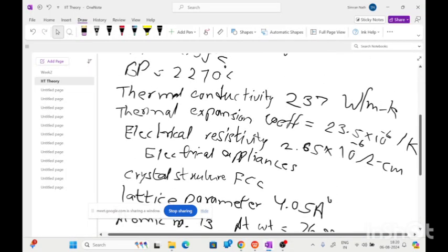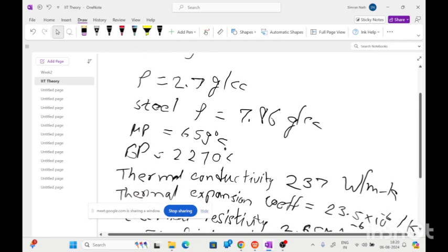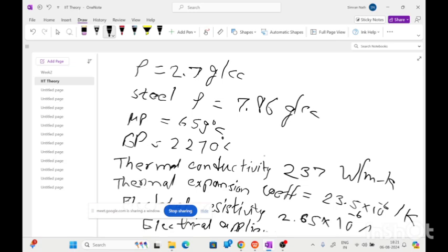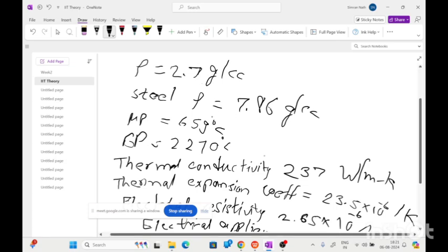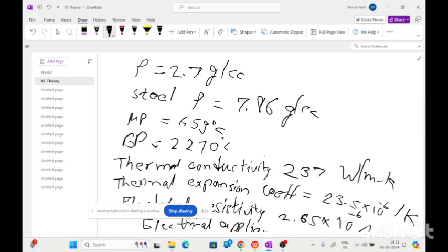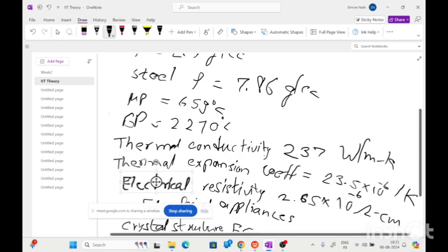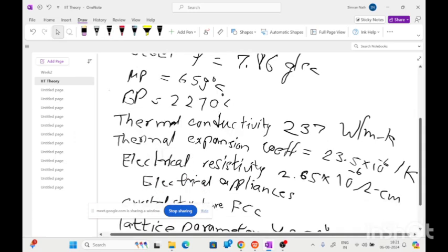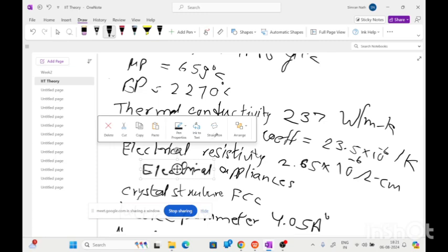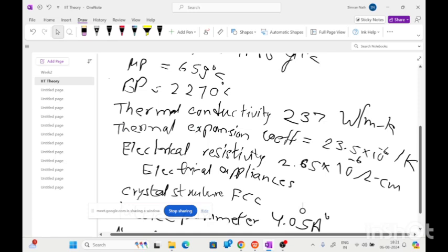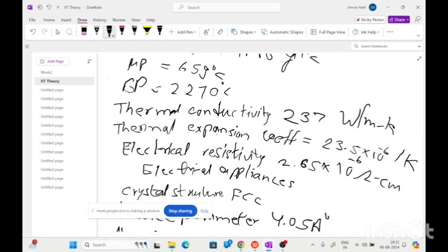So the aluminium properties. Aluminium is a non-ferrous metal. It has a density of 2.7 gram per cc, which is significantly lesser than steel and other metals. The melting point of aluminium is 659 degrees Celsius. The boiling point is 2270 degrees Celsius. The thermal conductivity is 237 watt per meter Kelvin, and the thermal expansion coefficient is 23.5 into 10 raised to the power minus 6 per Kelvin. Electrical resistivity is 2.65 into 10 raised to the power minus 6 ohm centimeter.